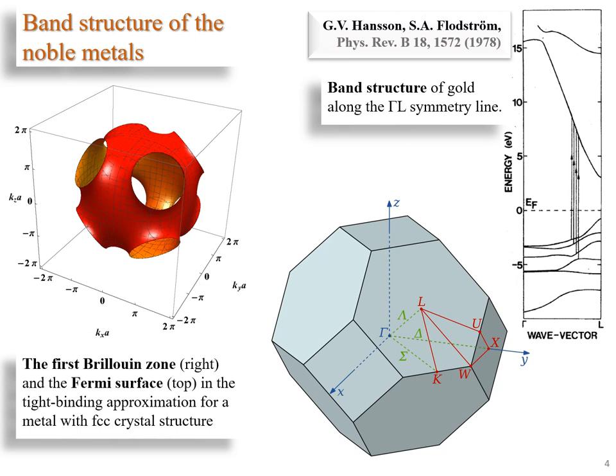Here we see schematic representation of the noble metal Fermi surface in the FCC first Brillouin zone. In the vicinity of the L-point, effective mass is negative in the direction normal to the Brillouin zone edge hyperbolic equal-energy surfaces or necks of the Fermi surface. There is a band gap for the bulk electron states in the gamma-L direction due to the sp-hybridization, where the surface electron states can emerge.